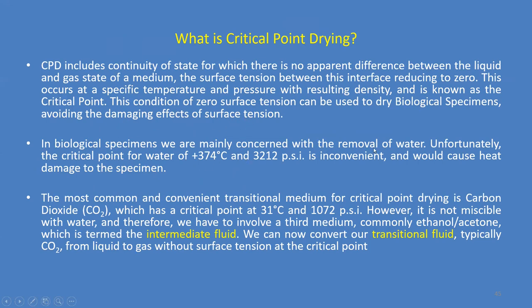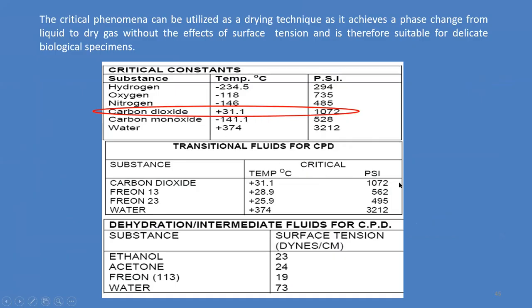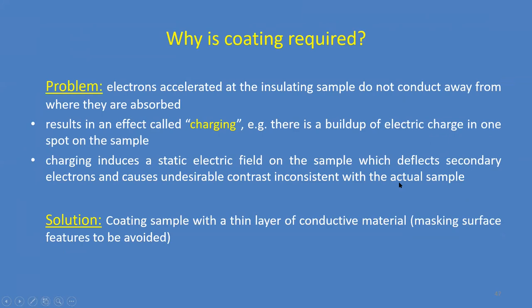Typically this is done with carbon dioxide, as we are concerned mainly with the removal of water. But the critical point of water is 374 degrees and 3000 PSI. You can't heat your specimen to such a temperature, it'll destroy your specimen. So typically we use CO2, carbon dioxide, which has a critical point of 31 degrees and 1000 PSI. Let's not go into the details of this. What you need to know is you need to use an instrument called a critical point dryer to perform this.